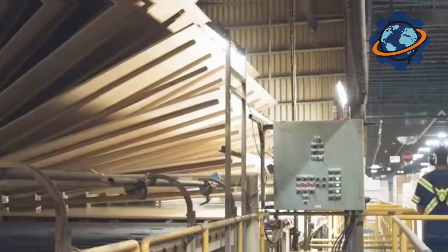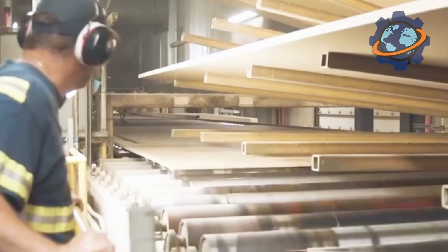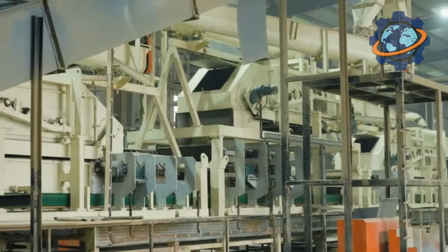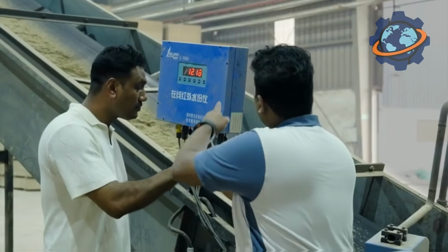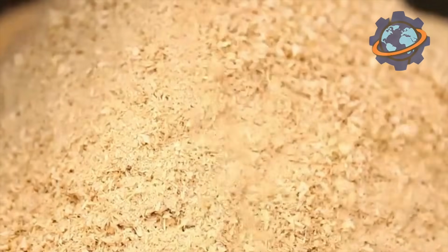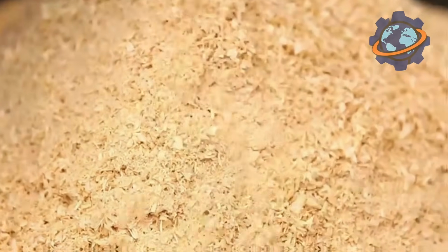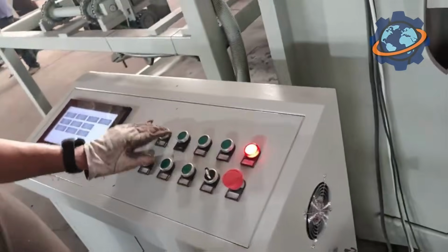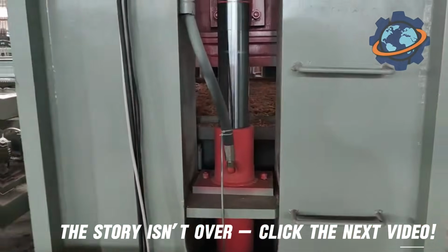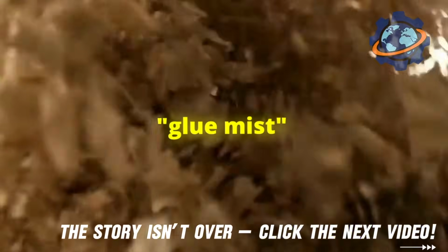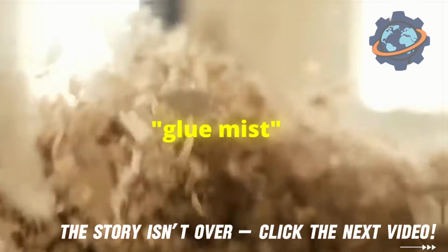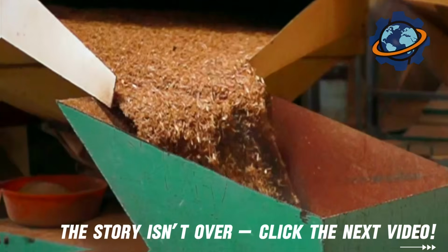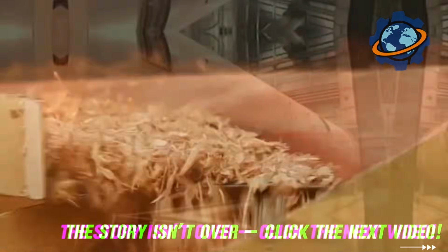Now it's time for the key component that will turn the loose mass of chips into a monolithic board, the binder. Most often, these are synthetic resins, mainly urea formaldehyde or melamine urea formaldehyde. The sorted chips enter special continuous mixers. Inside them, the resin is sprayed through nozzles, creating a glue mist that evenly envelops each particle of wood. The dosage of the resin is critically important and is usually from 6% to 10% of the mass of dry chips.